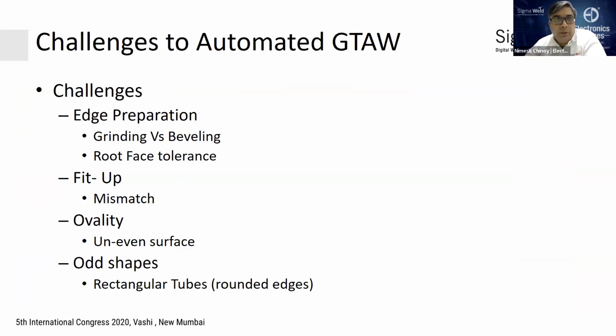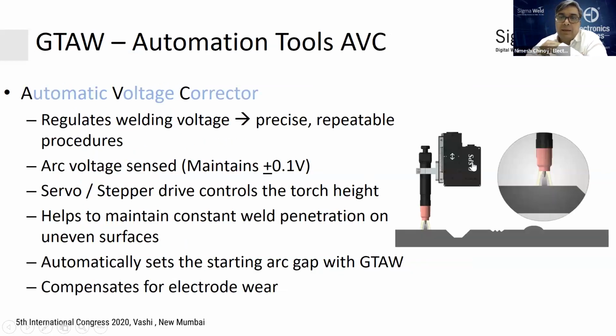Challenges to automate TIG welding: you have edge preparation issues, grinding versus beveling, root face tolerances, mismatch in fit ups, ovality, and odd shapes. They can be taken care of by using different kinds of weaving and oscillators, angular or straight. Some videos, but I'll play them later. You can also adjust the weaving speed, the dwell time on each end to avoid the lack of fusion, and you can set the weaving distances. Similarly, you can use something called an AVC or automatic voltage corrector, which follows the path by controlling the voltage, and it allows you to have very clear, irregular shapes can be managed by this as well.